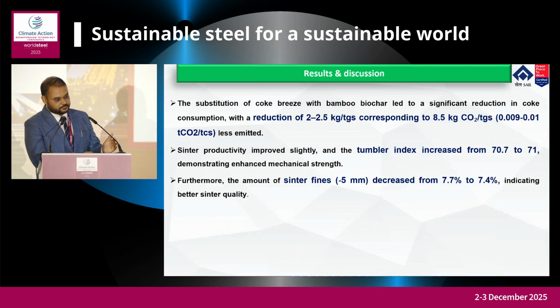Now, through this industrial trial, we could reduce 2 to 2.5 kg of coke breeze, which ultimately corresponds to a figure of 8.5 kg CO2, or 0.01 tCO2 per tCS, on an industrial scale. And improvement in productivity as well as sinter quality has been achieved at plant scale. This is a very encouraging trend, and not limiting ourselves to it, we are planning to go much further, both at lab scale as well as on an industrial continuous basis.